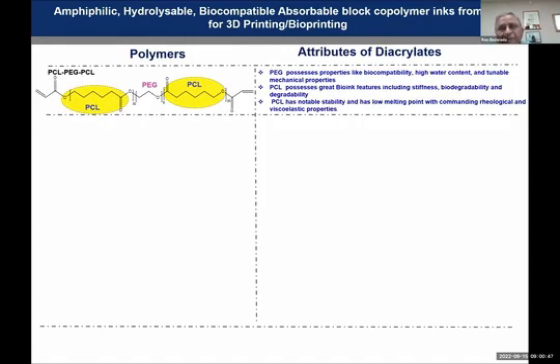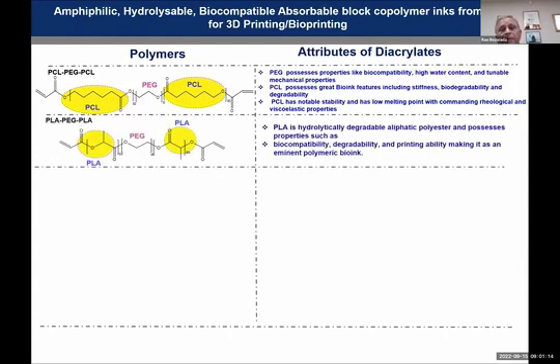This is amazing, having all these properties in one molecule: the hydrophilicity of PEG with different molecular weights and the hydrophobicity of PCL with different molecular weights, while solubilizing in water. It's a very unique set of properties. And we're making not only PEG-PCL, we're taking all the key ingredients of absorbable polymers, because these polymers give the strength, elasticity, control, and absorption, everything you need for a bioink.